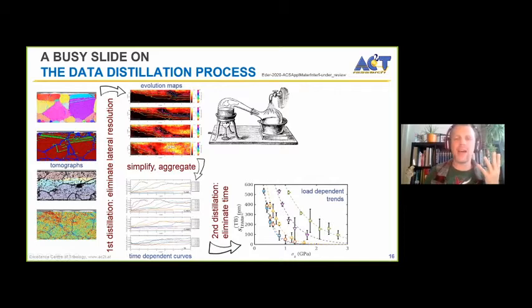Then we eliminate the time as a second thing. So we look at these graphs, we see there's something interesting going on here. We're going to check out when exactly the twinning activity takes off. So this is what's plotted here as an example of something that you can plot as a function of the normal pressure, normal load. This would be the distance that you have to slide until, for this type of system, the twinning activity starts to surge. And then you can fit curves into these load dependencies, and you will always wind up with some typical normal stress that is typical for this alloy and for this process or phenomenon, or ideally a mechanism.